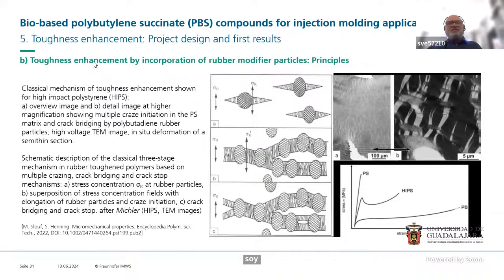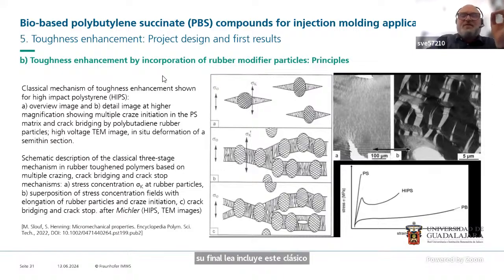So finally, the second approach is to use the classical impact modifiers, the classical toughness enhancement idea. That means if we incorporate small rubber particles, then when we have a mechanical load applied to the material, we induce deformation processes at these soft rubber particles. The soft rubber particles act as stress concentrators and we produce a lot of mechanical deformation just in the surrounding, here in the polar region, in the equatorial regions of the rubber particles. And we do that multiple times. So if we have a lot of these small rubber particles, we induce cracks or micro cracks or crazes in large parts or huge parts of the volume.